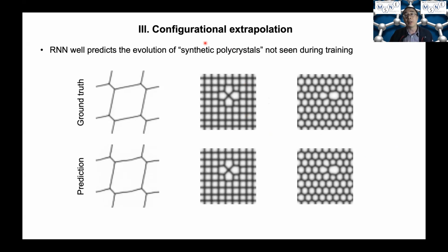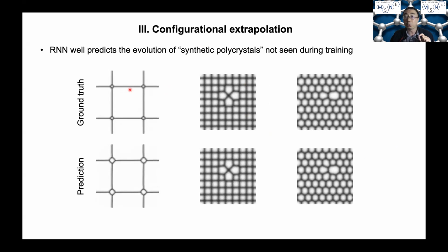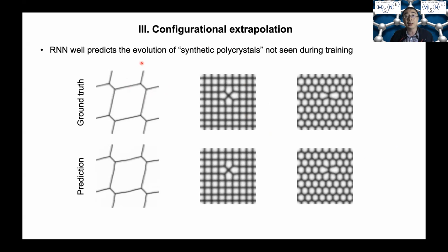And we also did another type of extrapolation test in the configurational space. So here we let the trained RNN model predict the evolution of some synthetic artificial polycrystal structure it has never seen in the training data set. So for example, here we have a structure with 8 grains arranged in an ordered fashion in the system. So this is something that's very different from the polycrystal structure in the training set, which was generated by the Voronoi tessellation and looks more like a real polycrystal grain structure.